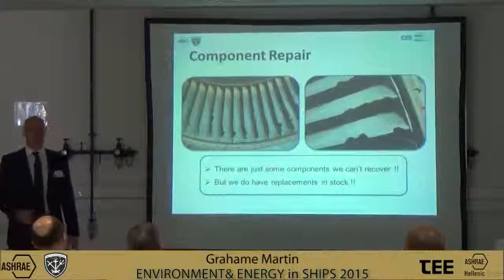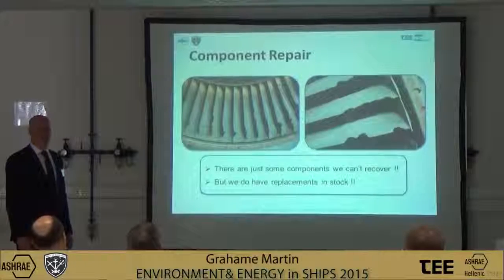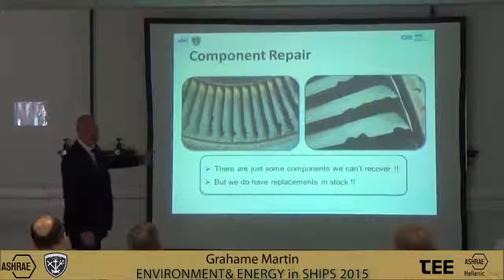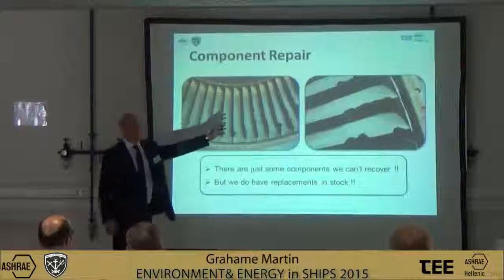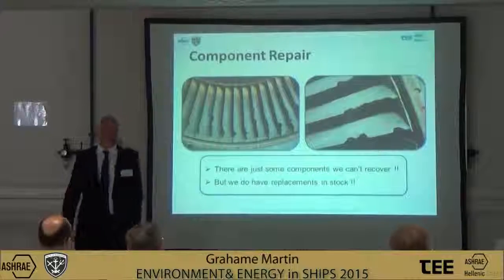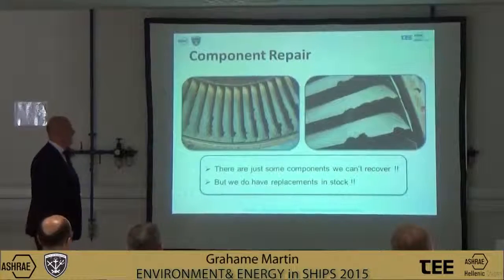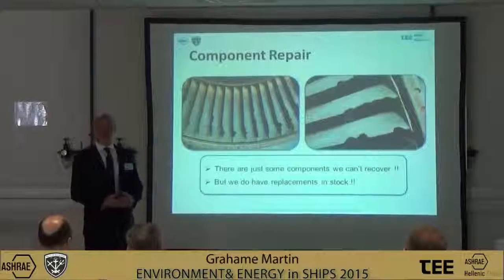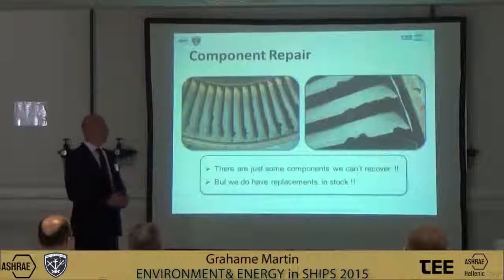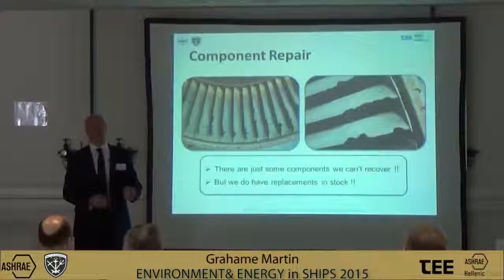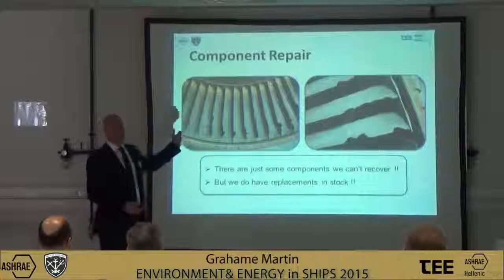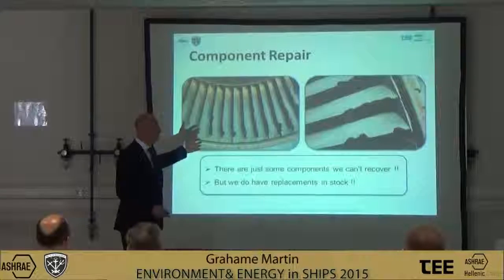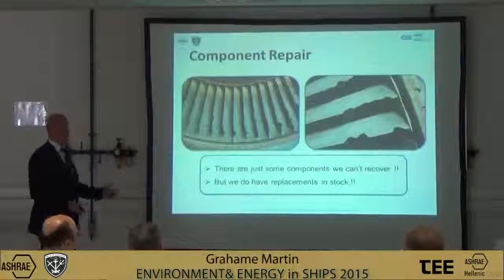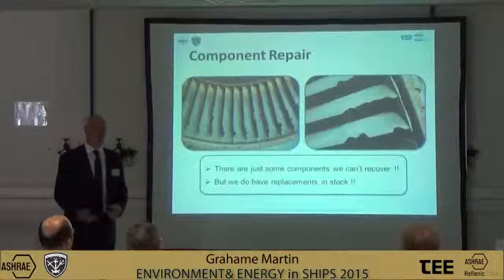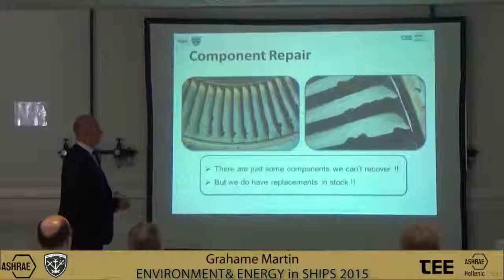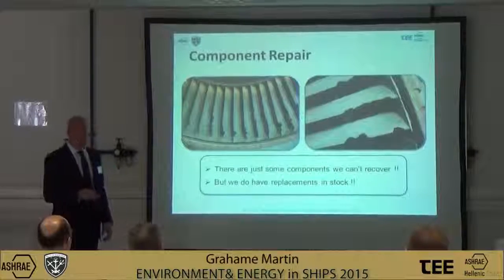As you can see, there are just some components that we can't recover. This is pretty severe damage. Again, I'm hoping everybody understands what we're looking at here, but that's basically the LP turbine section of an Olympus gas turbine, where the customer, through lack of maintenance, allowed one of their fuel nozzle shrouds to come off, and it only has one way to go, and that is through the turbine section, leaving nothing left. We can't recover it, but of course we have a huge amount of stock, so we can replace these turbine blades, balance the machine, and then get it back into service again.